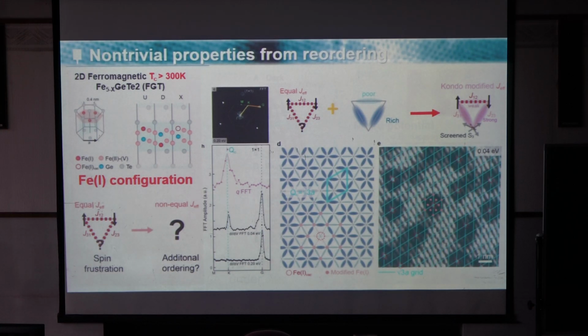And from the real space and k-space analysis, we find the Kondo behavior also has the same electronic period as the charge density wave. Also, they are in phase, so we can utilize this information to explain the new spin ordering in this material. We also extend this charge distribution to large scale, and it indeed comes from the root 3 stripe electronic period.